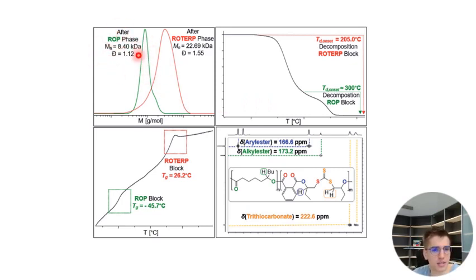So this is the GPC after the ROP stage of the lactone, and this is the GPC after the sulfurated ROTERP stage. And it grows nicely. Then of the isolated block polymer, you could really see a stepwise decomposition, with the sulfurated block starting to decompose at about 200 degrees and the lactone block starting to decompose at about 300 degrees. And in the glass transition temperature, they phase separated. We could later also see this by AFM and by SAXS.